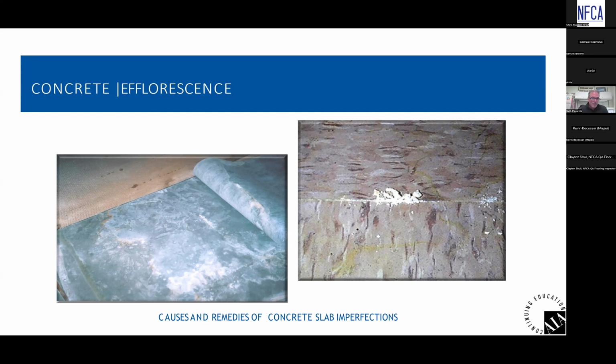The left picture is pulling back some vinyl material, and we're left with whitish residue on the underside, and that's natural salts from the concrete, indicative of a moisture problem. That process of water taking the salts to the surface is called efflorescence. So yes, the efflorescence is a problem because it's a contaminant, it can cause a bond problem, but it's a result of excessive moisture. So yes, we've got to remove the contamination, the salts, but we also have to address the moisture issue too, that is the cause of the efflorescence.